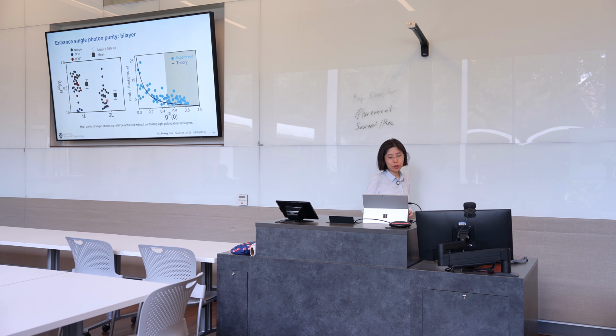In addition, if we summarize the G2 as a function of the peak to background ratio, we can see with a relatively high peak to background ratio, you can easily achieve a lower G2 or high single photon purity. So suppressing the background is an effective approach to achieve high single photon purity.